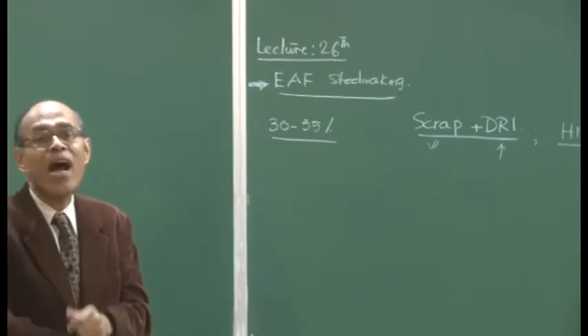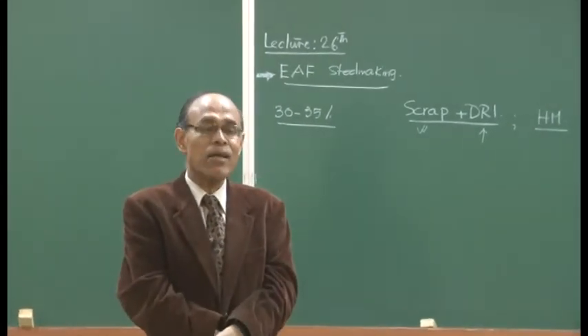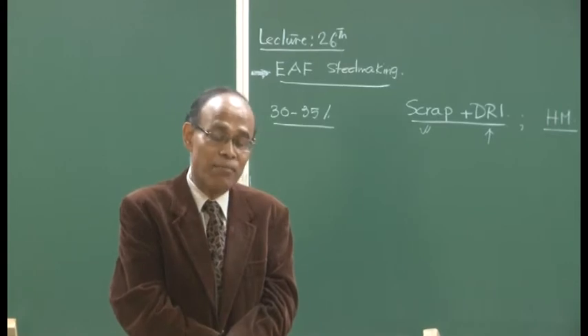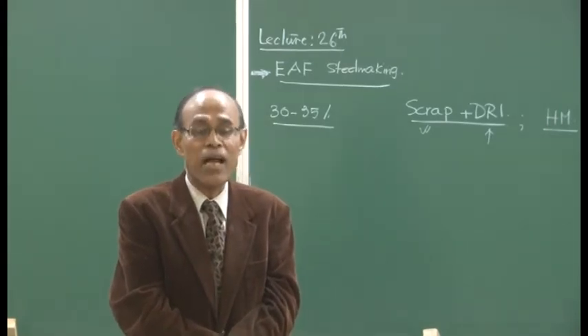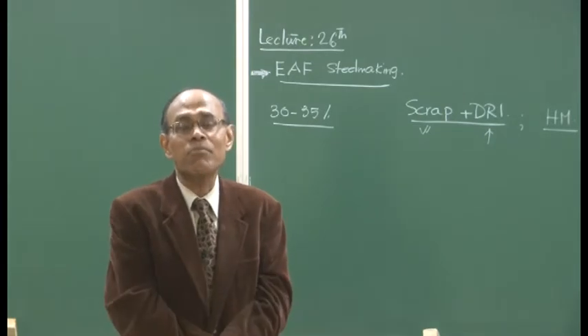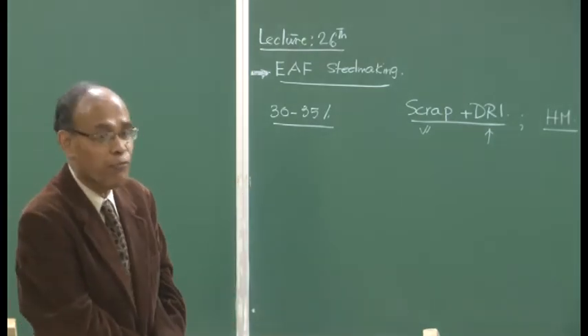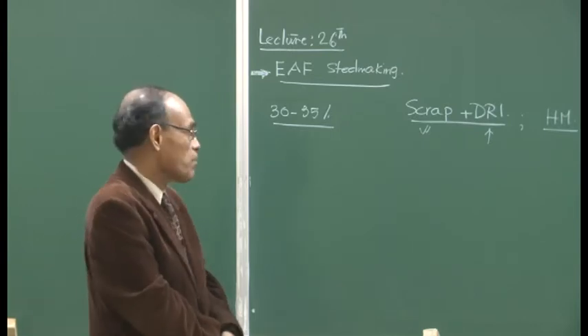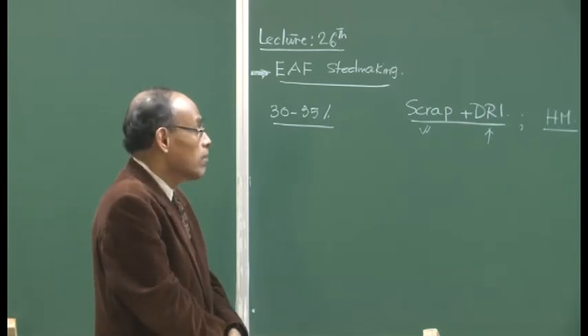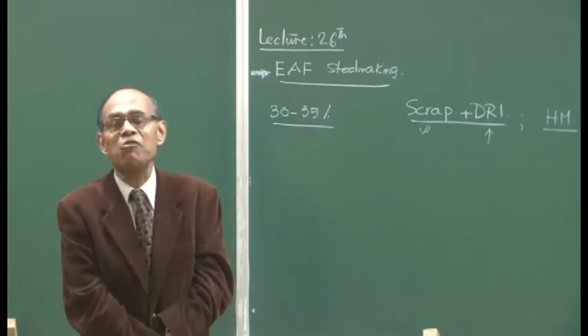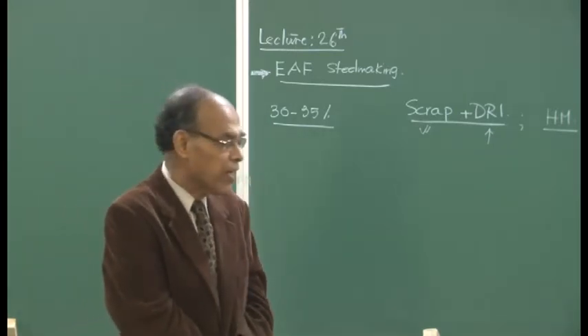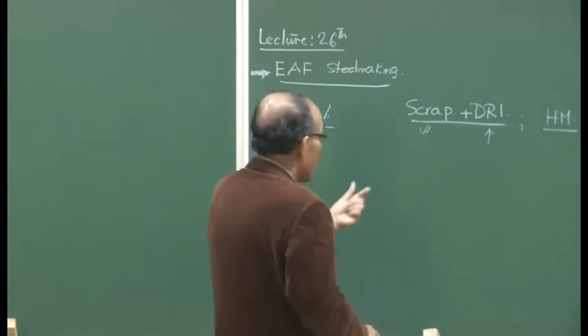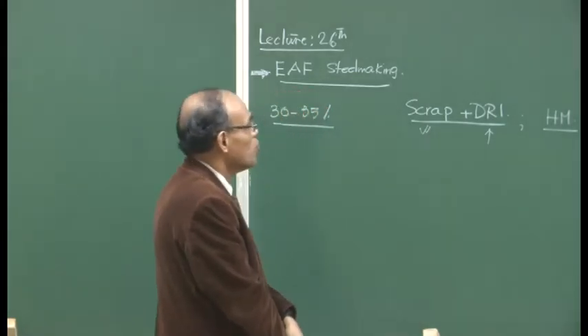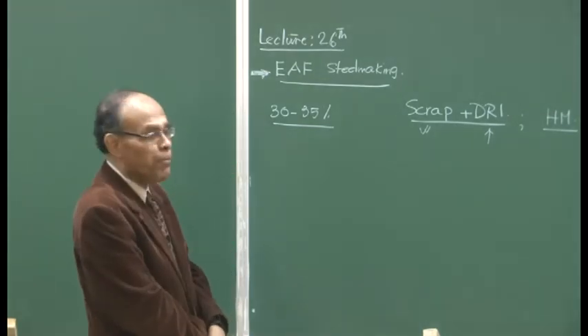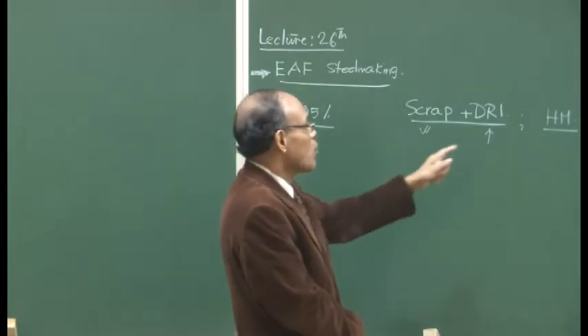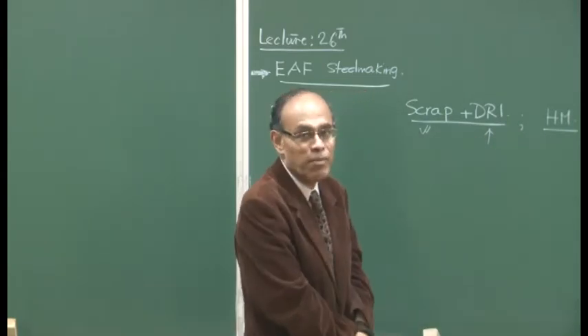There is a competition between the arc furnace steel making and BOF steel making, because I have mentioned that the tonnage is huge, and the cost of production is also enormously low in the BOF route. Of course, we will see that the energy consumption per ton of steel produced is more there, but the traditional arc furnace used to take very long refining periods, and so making the arc furnace really competitive to BOF steel making necessitated a lot of developments, and one such development is the introduction of hot metal as a charged iron bearing feed material into the